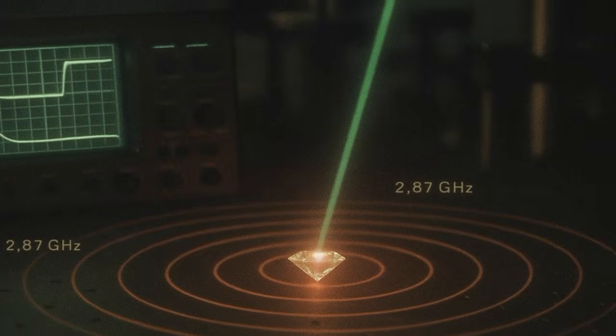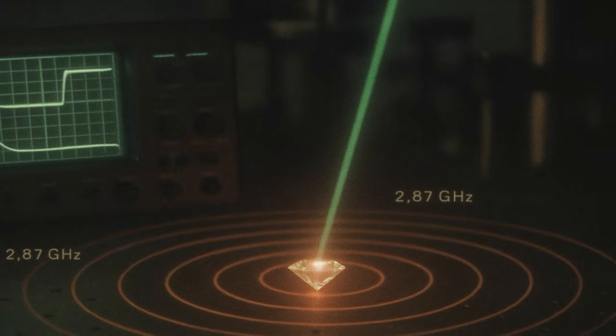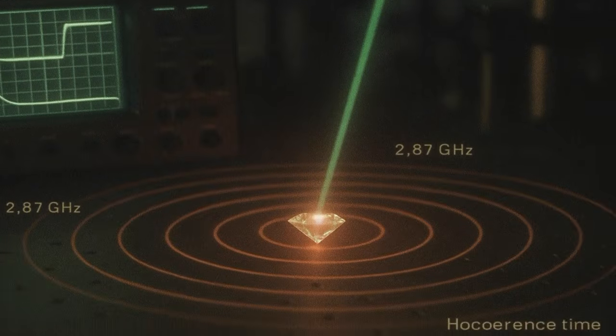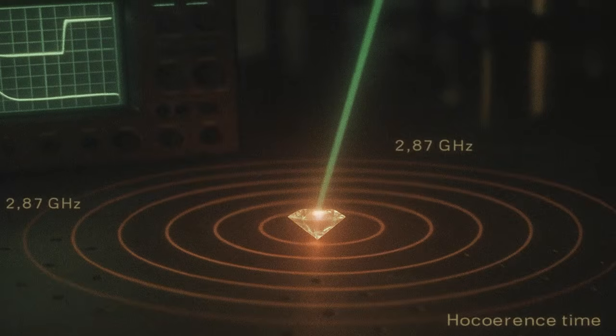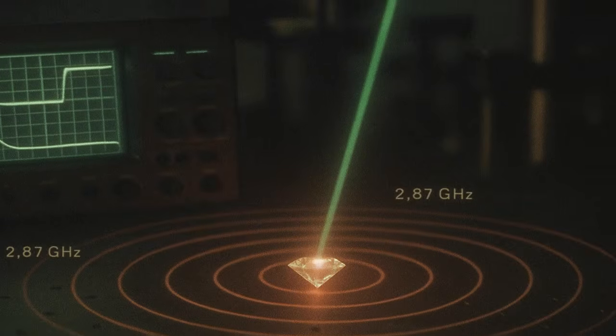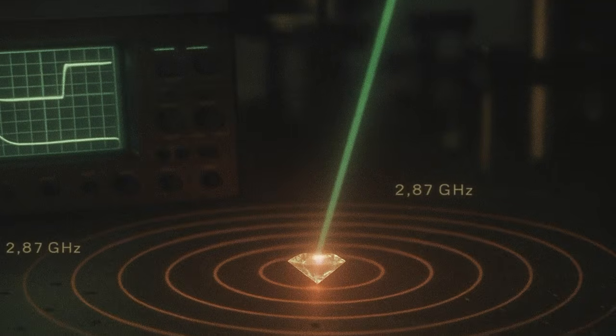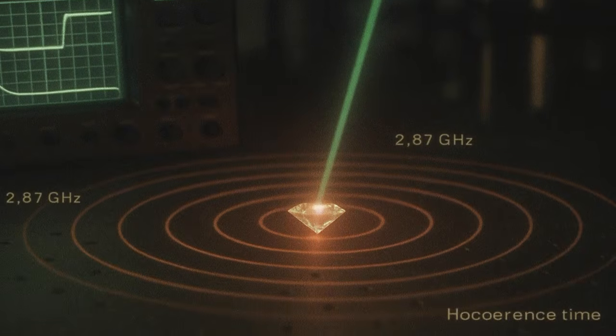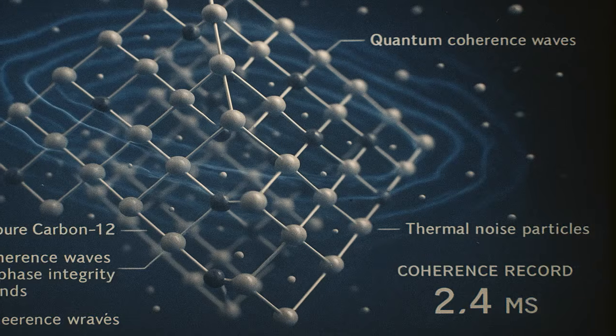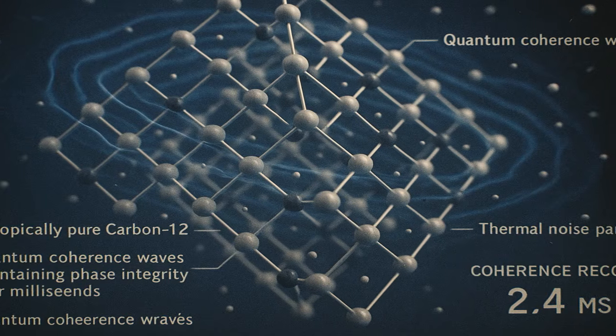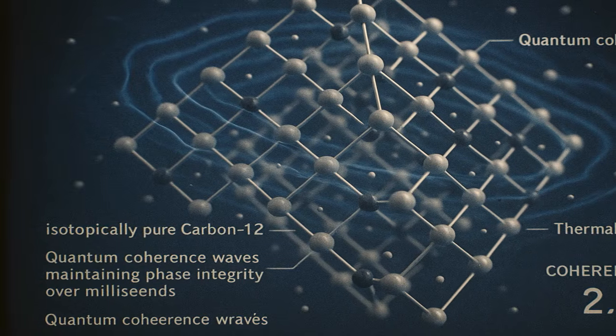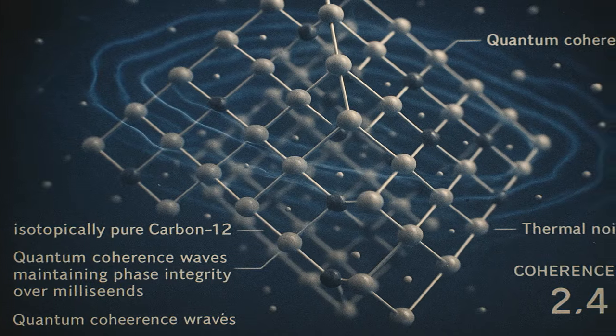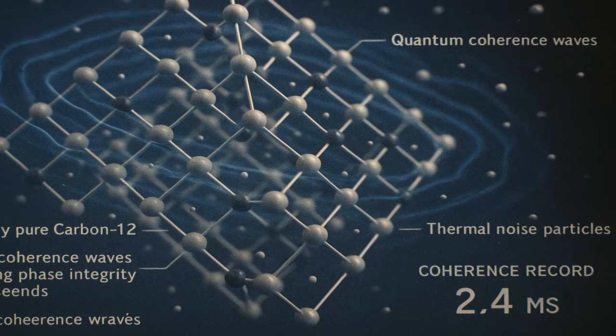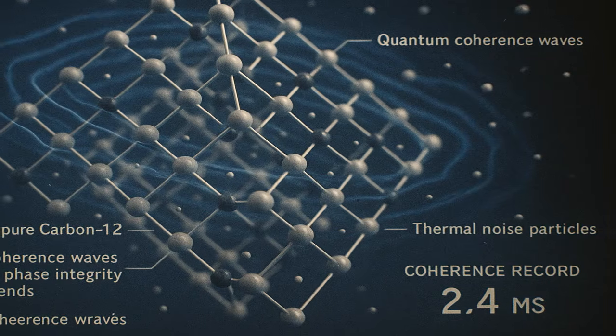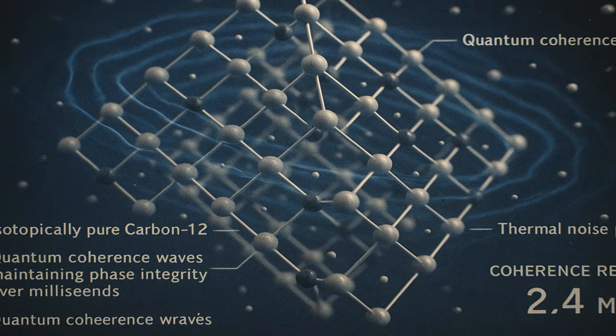NV centers don't. They sit in a diamond lattice with a 5.5 eV bandgap. Nothing in a biological environment has enough energy to damage them. You can image single nanodiamonds under continuous illumination for hours and the signal stays constant. Studies from 2009 compared NV nanodiamonds to cadmium selenide quantum dots. At saturation, the nanodiamonds emitted 3 times less intensity than quantum dots, but the quantum dots blinked on timescales of milliseconds. The nanodiamonds never blinked. For long exposure imaging, the diamond is brighter because it's always on.